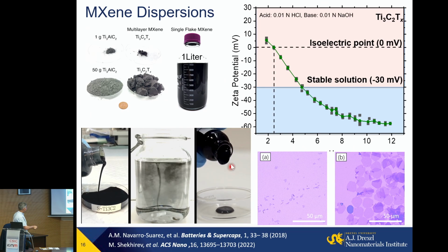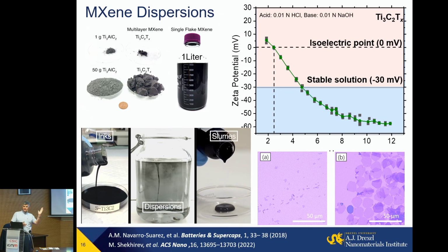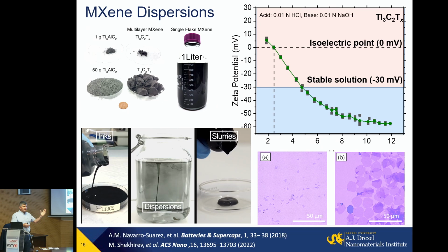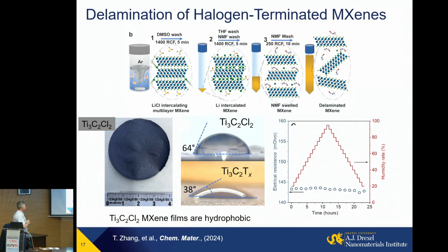But if we have a solution which contains either very large particles at smaller concentration or a larger concentration of smaller particles, we can get a liquid crystalline solution. So flakes cannot freely rotate in solution anymore, and they get very well aligned when you want to draw fibers, or make patterns and films by doctor blading or screen printing, or do 3D printing with these materials. So again, it's just pure MXene with no additive. So you control viscosity and design colloids for processing, and process from pure water with no additives, very important.